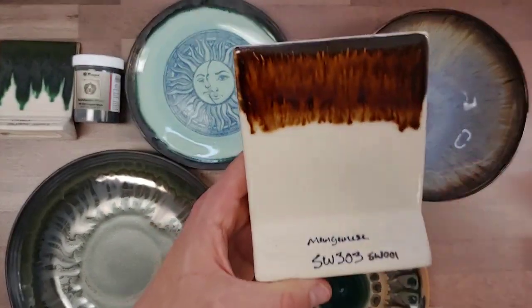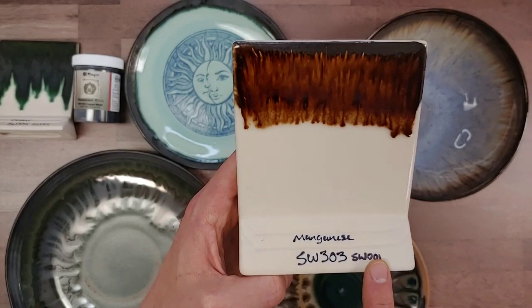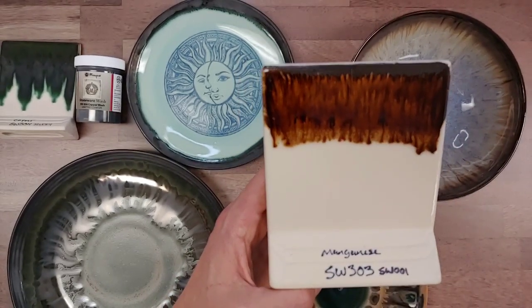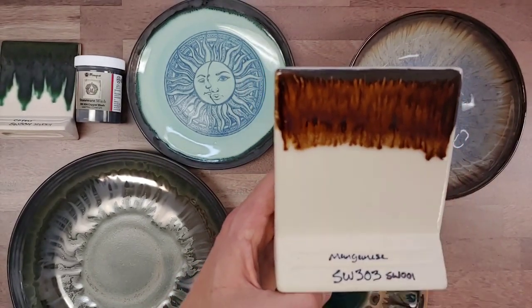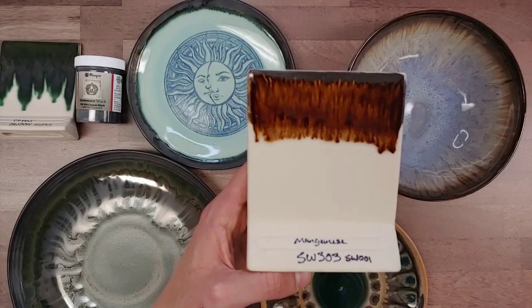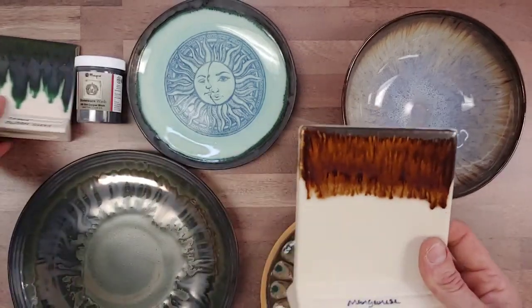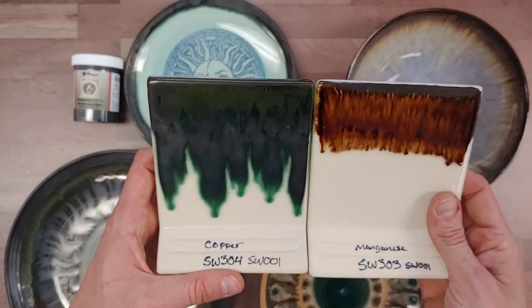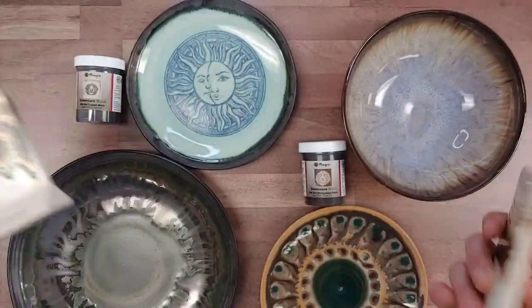On the back you get this beautiful brown variation when it's layered with other glazes. Here the manganese wash is layered with our stoneware clear and it does create a little bit of movement — you can see the line that's created. Just one full strength coat with clear glaze on top, and there is some movement. So again, with a stable glaze it has movement; with a mobile glaze it will create even more. The thickness of your glaze application and wash application will also influence the movement — more coats of wash or glaze will make these move more.